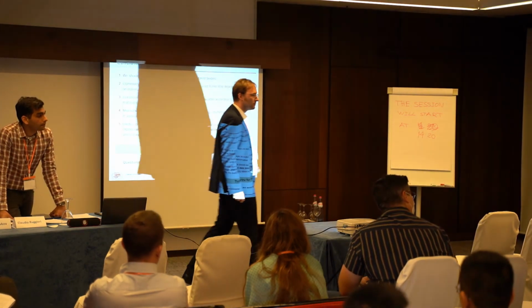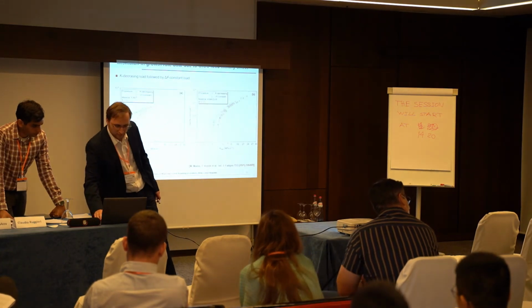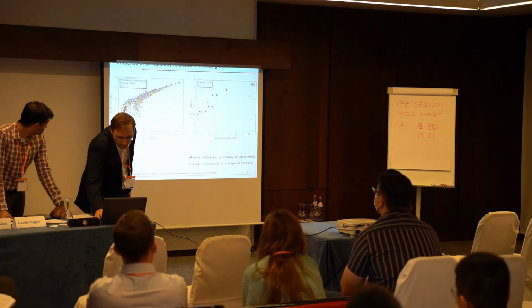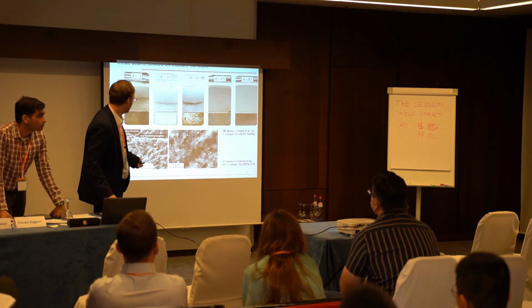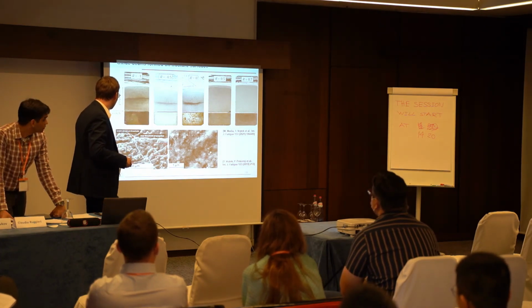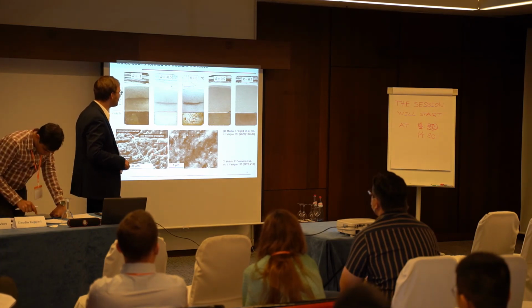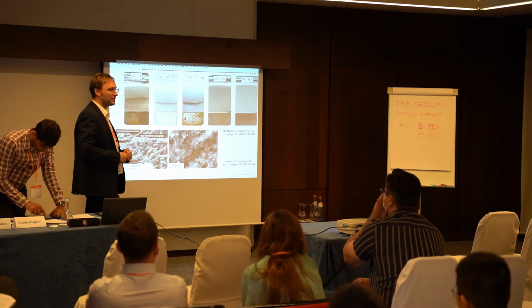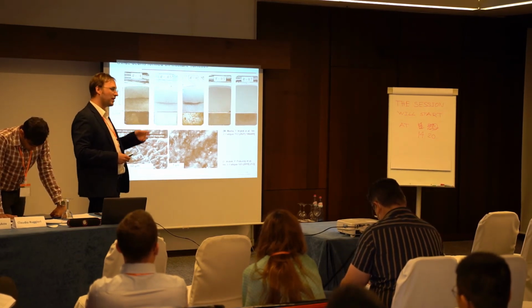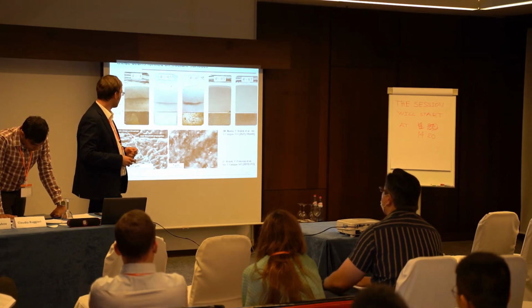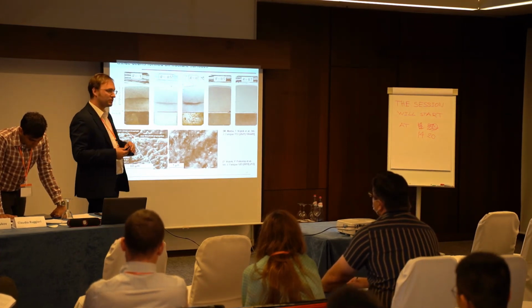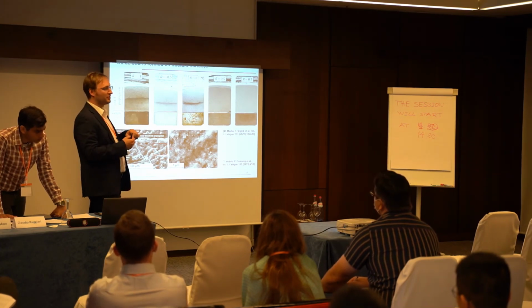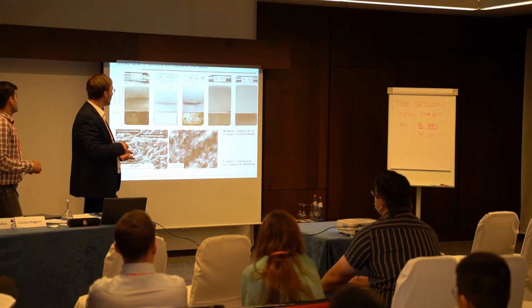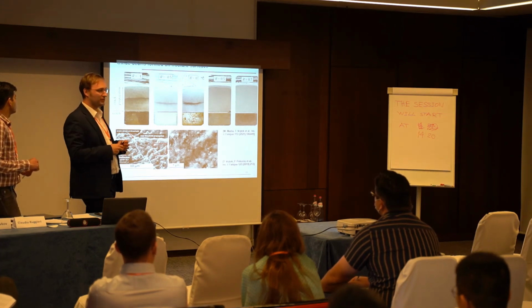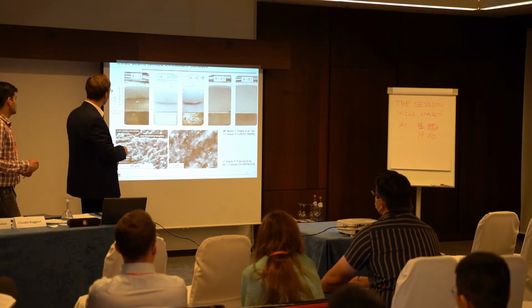In slide 14 or 15, you mentioned that you can see oxide particles on some... yes, what load ratio was this tested at? This was 0.1 or -1, because we had almost the same growth curves in terms of K maximum if we apply 0.1 or -1. And actually the growth of oxide really is caused by a large compressive stress just near the crack tip. And the fact that at -1 we have a compressive stress throughout the whole fracture surface is not significant. The stress is too small. Otherwise we would have the whole surface black, but we only have it very close to the crack tip and near the threshold region.